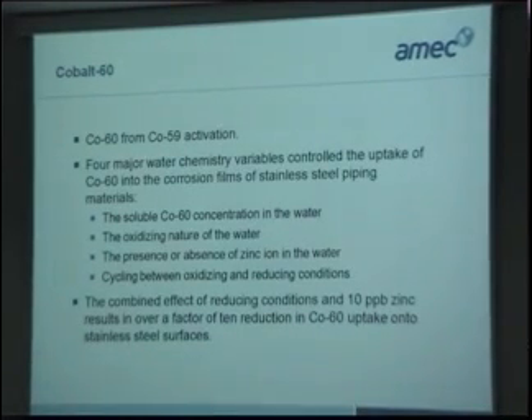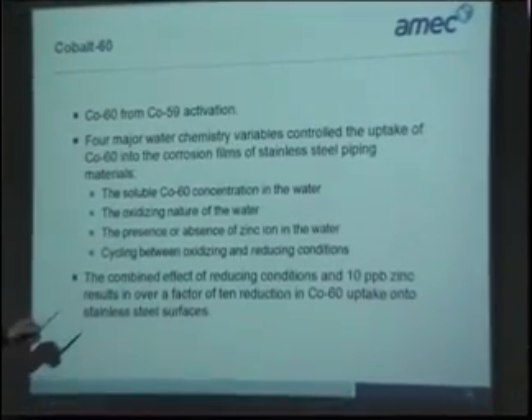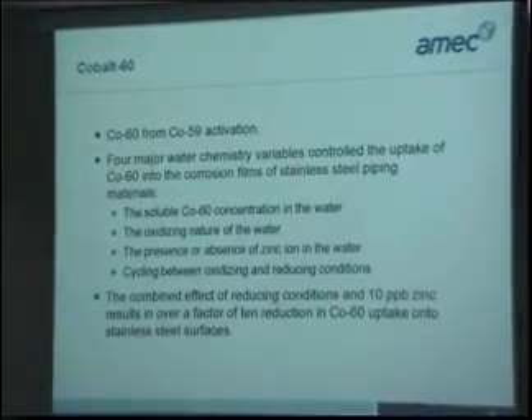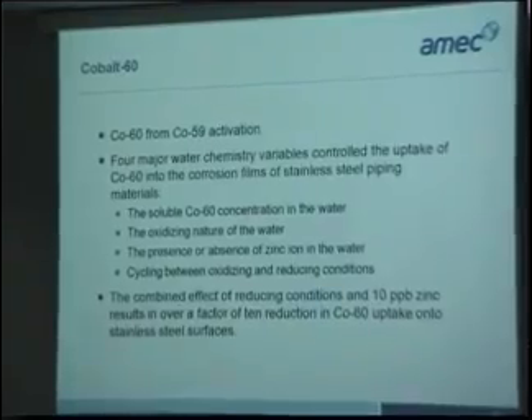So invariably local shielding of turbine components is required for dose management. Cobalt 60 is really an issue for both types of water reactor, activated from cobalt 59, which is always an impurity in steels. The main contributors in BWRs are the soluble concentration in the water. And because the water is of a more oxidizing nature than a PWR, you're going to increase the solubility. You can mitigate that with zinc and cycling between oxidizing and reducing conditions. It's found that the effect of reducing conditions and adding zinc will reduce your cobalt 60 by an order of magnitude.